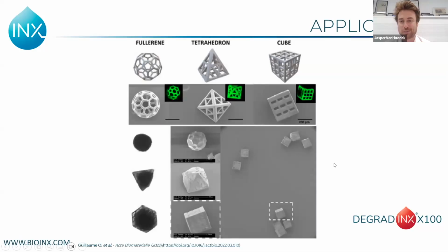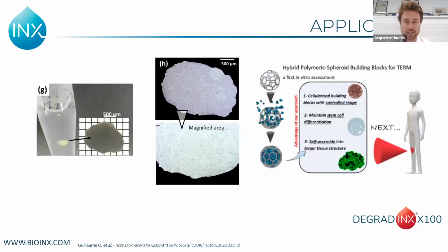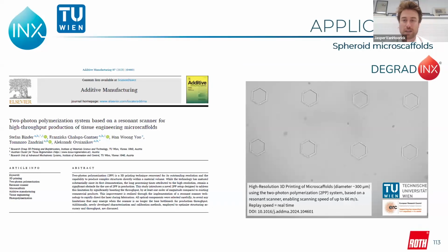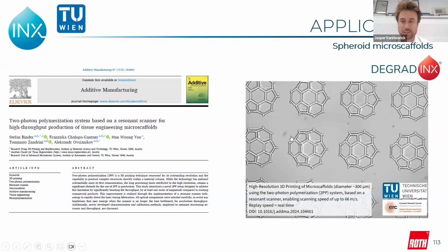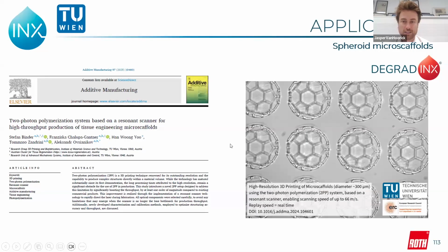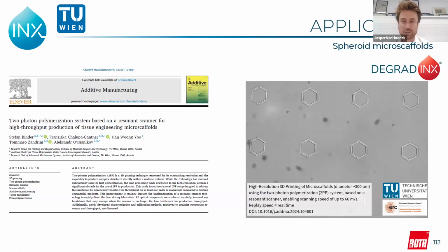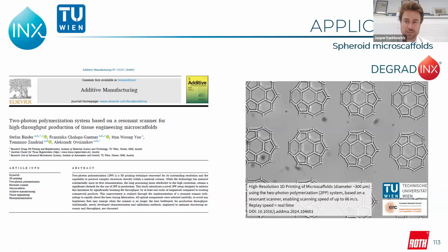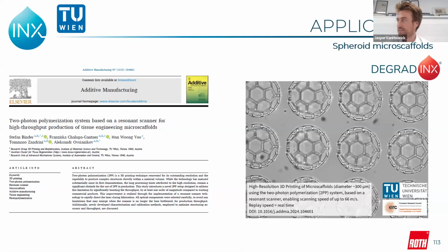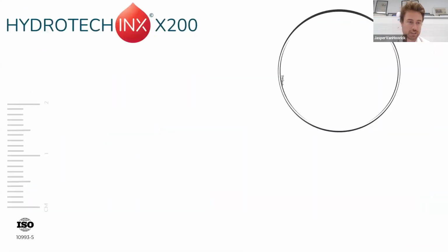And with this, you can actually do stuff which is against nature in a way. You can have cubic or pyramidal spheroids should you want to. And the idea is that over time, the material breaks down and your tissue forms. They even managed to print thousands of them and actually fill some cracks in defects. So you can see here a whole cluster of these spheroids with cartilage cells. By now, they also made a new bioprinter, which is a lot faster. So this is real time. This is not accelerated anymore, where they can 3D print these cages 12,000 per hour, basically. Now they also did some in vivo tests, which were very promising with this technology. I see that there's a picture missing, so I'll skip this.